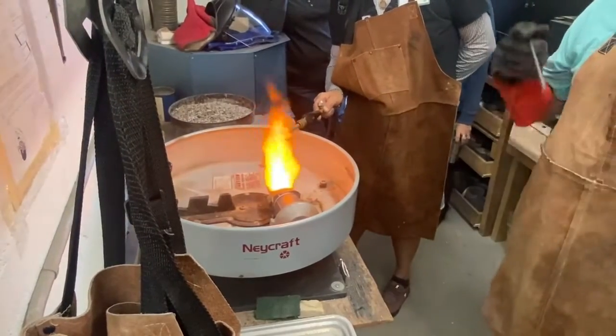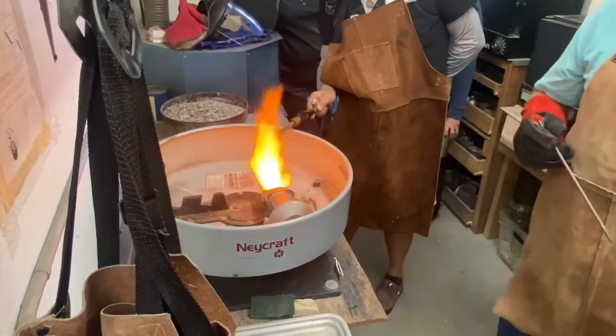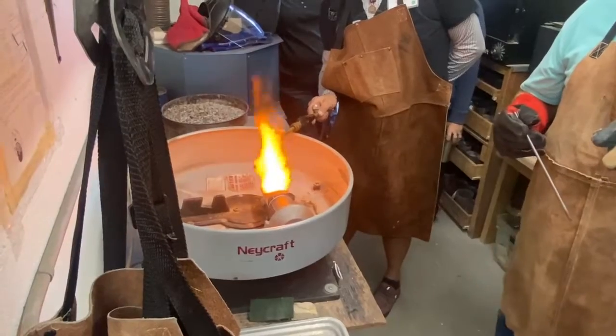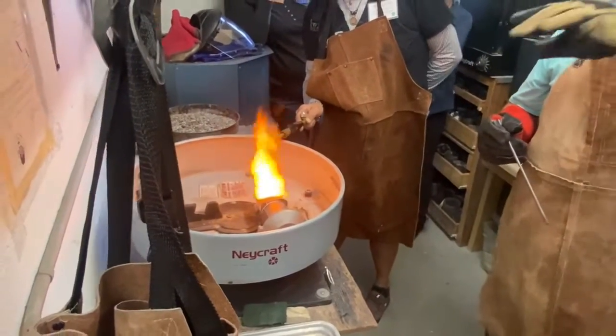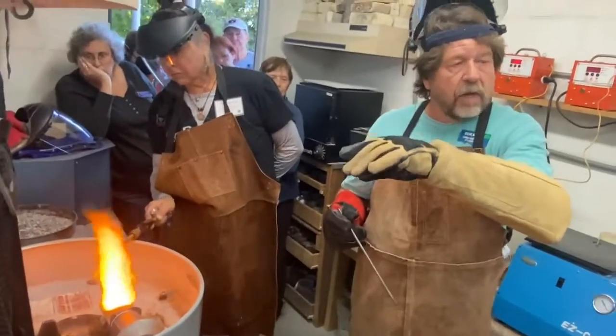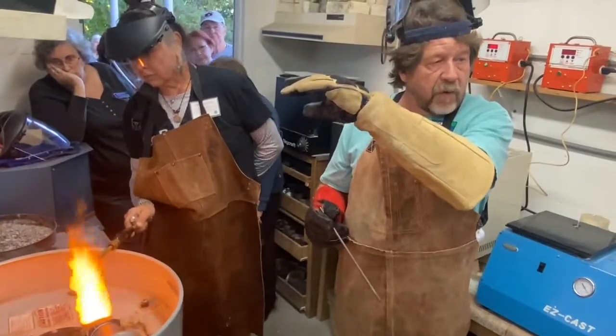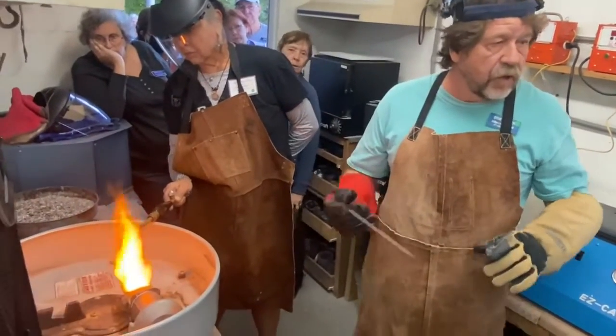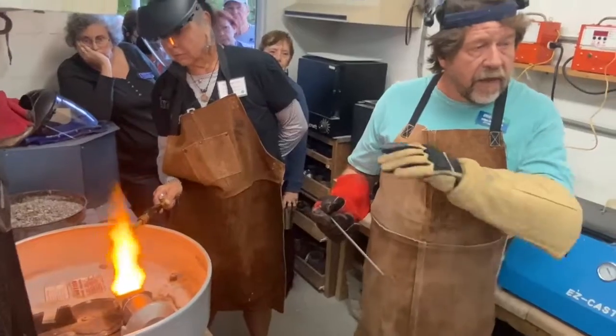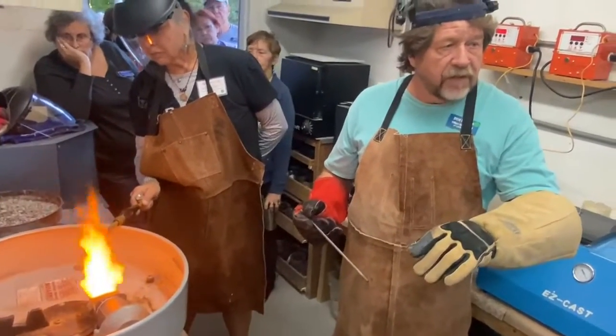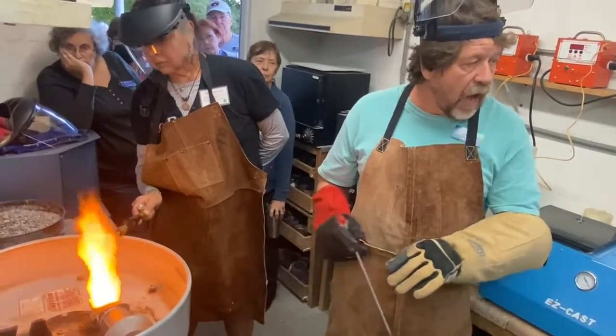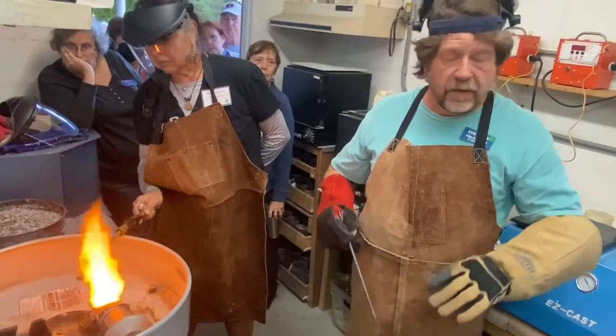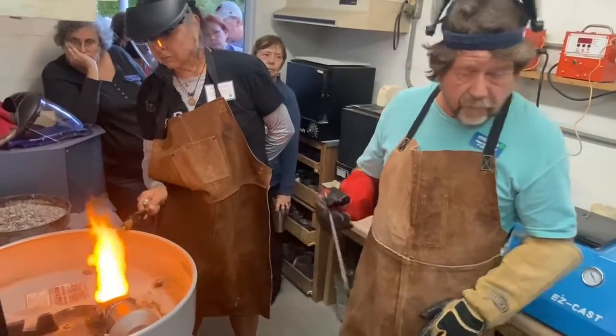Been in the kiln since 7 o'clock this morning, ramping up to a burnout of 300 degrees for several hours, then up to 900 degrees to soak, then it goes up to about 1200 degrees to fully burn out the wax and cure the mold, and then it ramps back down to 900 degrees, and it's been holding that since about 4 o'clock. So we're definitely at 900 degrees, which is our casting code.